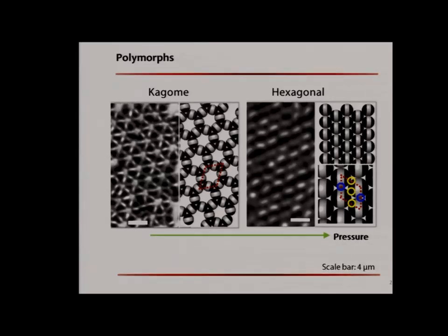You may see polymorphism here, and I'd like to offer you another perspective. We are able to make two stable lattices from different conditions from the same building block. That means now we have a responsive material. The porous film can just collapse into the closely packed film with its pore size and hydrophobic hydrophilic patterns totally tunable. And you can switch the film in these two configurations back and forth with application or the removal of the lateral pressure.